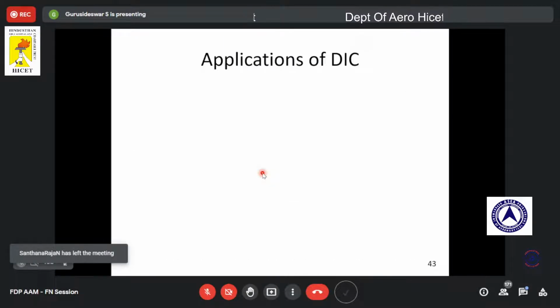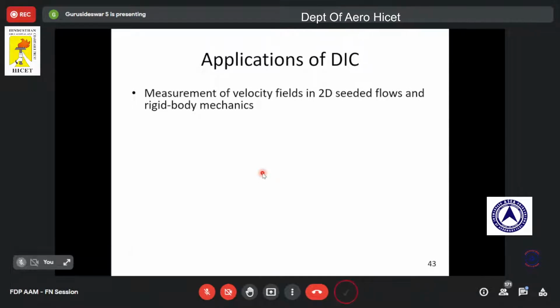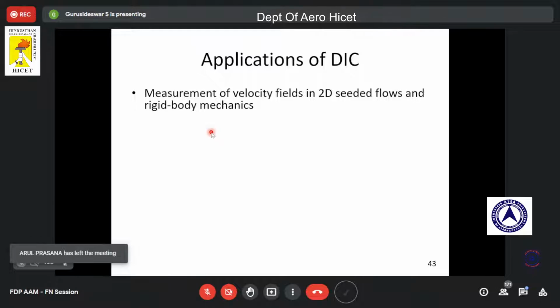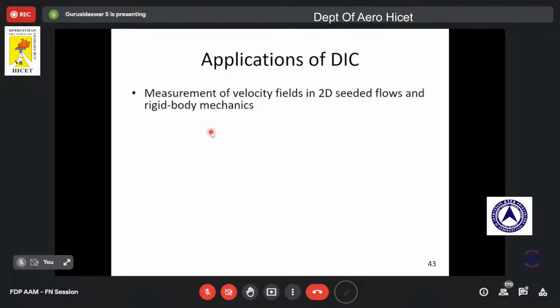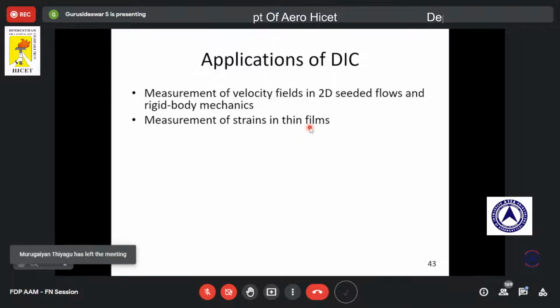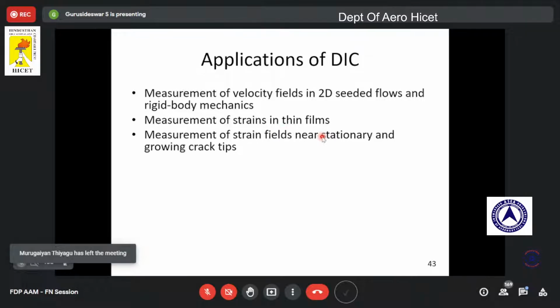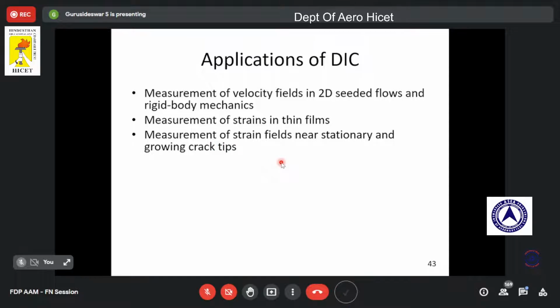Fine. Now, applications of DIC. I want to give you a quick idea about the applications. As I told earlier, DIC is a full field strain technique; I can get the strain data over the entire sample surface. So it is used in fluid mechanics to measure velocity fields, and we can use DIC for thin films, because it is difficult to use an extensometer or strain gauge on a thin film. With the help of DIC, we can measure strains from thin films, and we can measure the strain field near a crack tip.